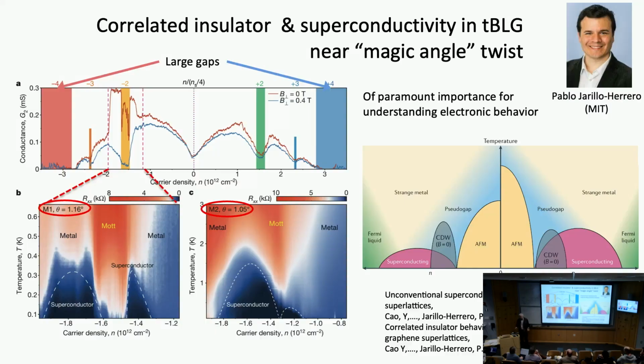And this made things very exciting, because if the phase diagram is so similar, then that implies that the physics is very similar. And then you could imagine studying the very exciting and interesting and complicated physics of the high temperature superconductors, which are difficult to make from a chemical point of view and to control all the doping and so on, in a very, very simple system, twisted bilayer graphene near the magic angle. And that's one of the main reasons why the field has exploded so much, because it gave us a practical, simple system on which to study essentially the same physics as what is more or less seen in high temperature superconductors. By the way, high temperature superconductivity was discovered in 1986. So that's 40 years ago. I remember it very vividly.